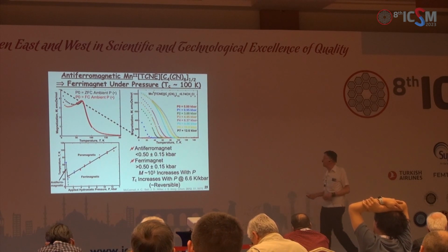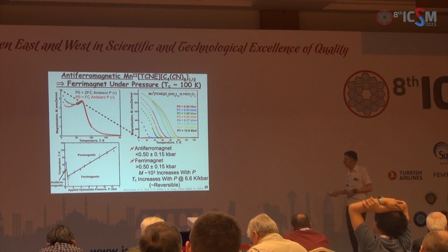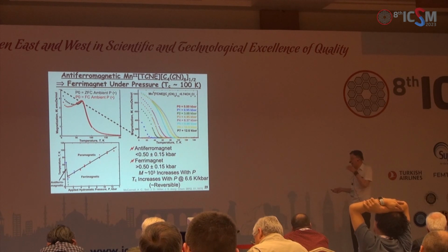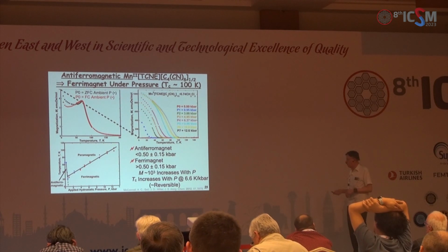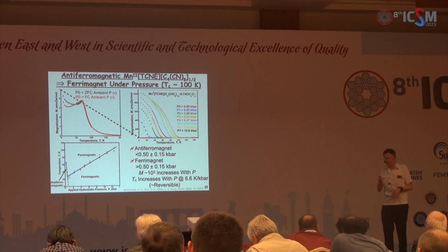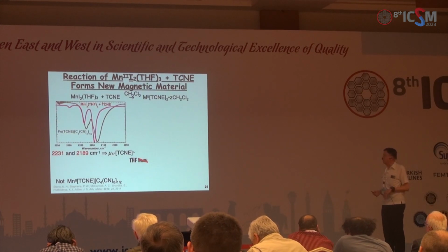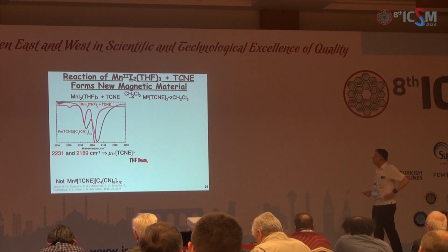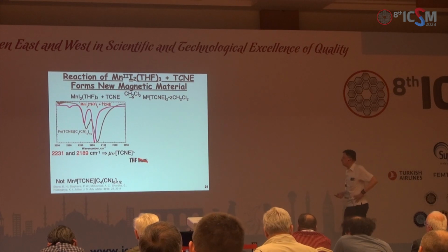So in fact, it's an antiferromagnet up to 0.5 kilobar, and a ferrimagnet above that, with magnetization increasing up to 3 orders of magnitude. We don't fully understand the structure of this—it's an interesting magnetic material. Now, as a chemist, we play around with all sorts of things.